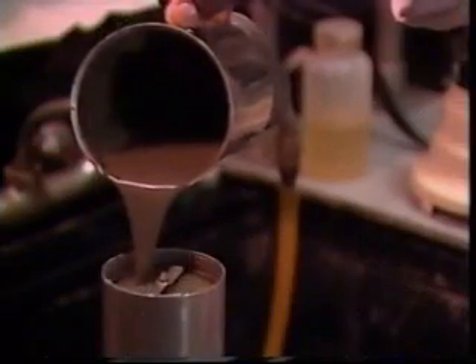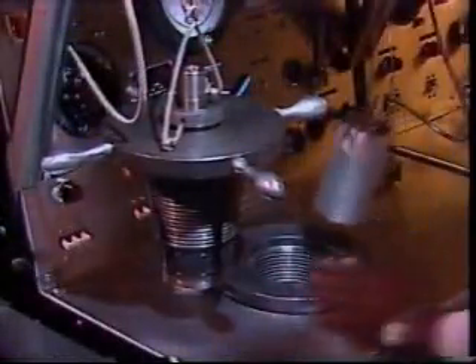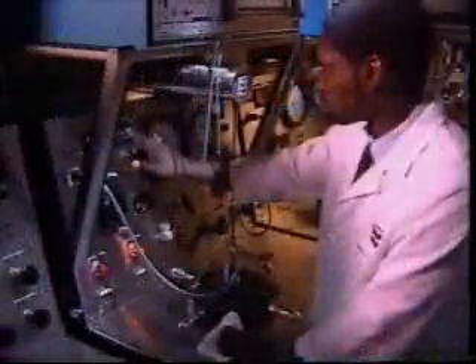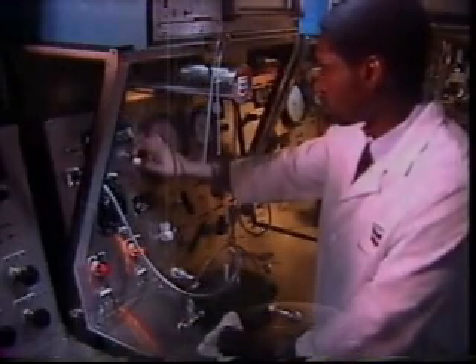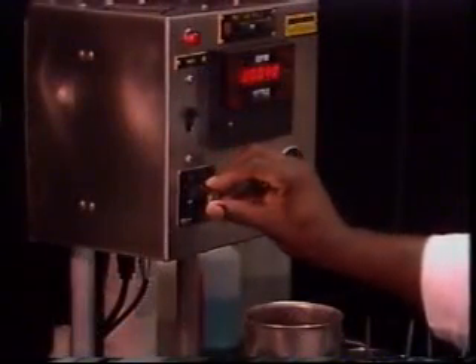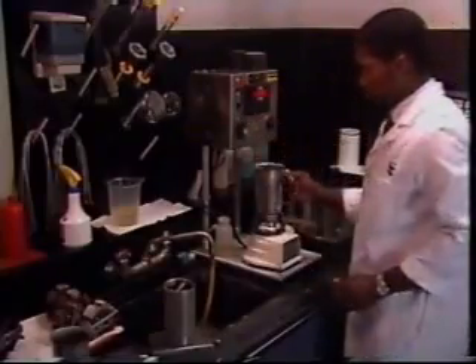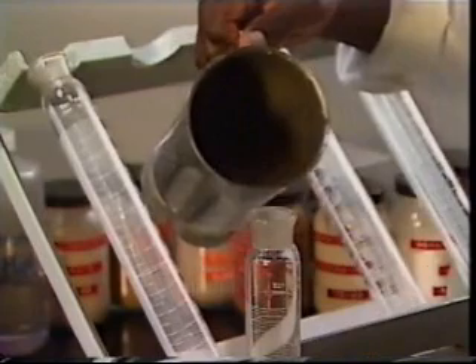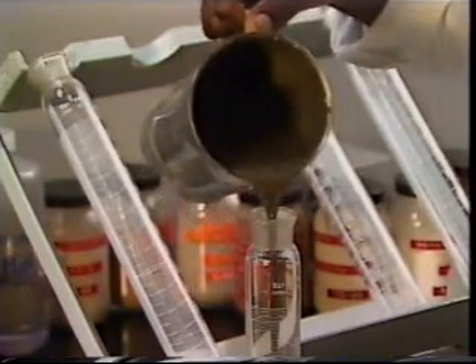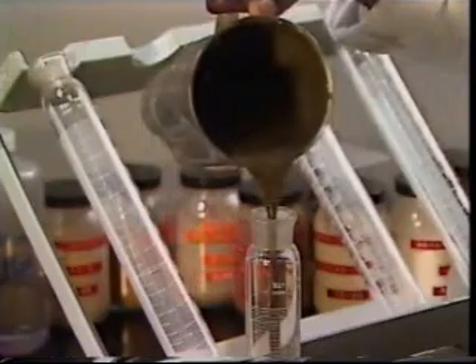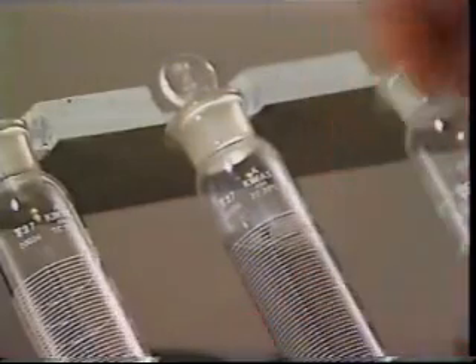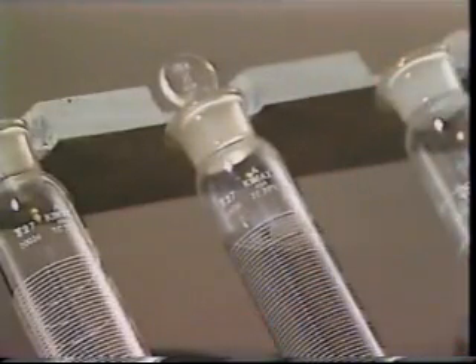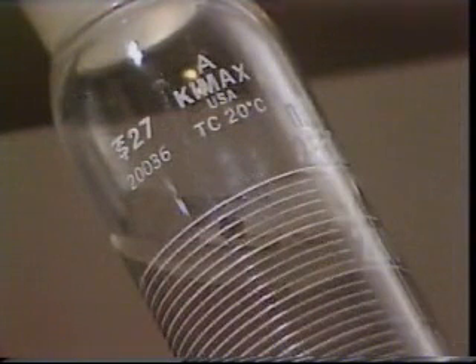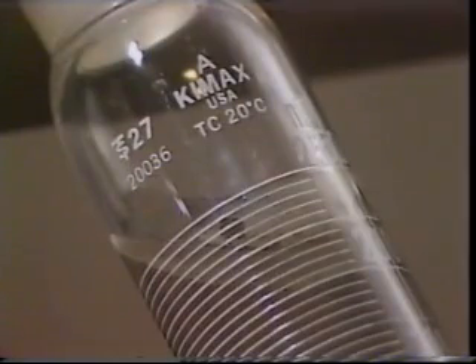In the test for free water, the cement slurry is stirred in a consistometer for 20 minutes, allowed to stand for a period of time, then remixed in a blender for 35 seconds, and placed in a graduated cylinder for 2 hours. Since free water volume can be significantly affected by hole angle, free water tests for deviated wells are often conducted with a graduated cylinder placed in various positions, in addition to the API-specified vertical position. The supernatant water is then measured. Its volume should be less than 3.5 milliliters per 250 milliliters of initial slurry.